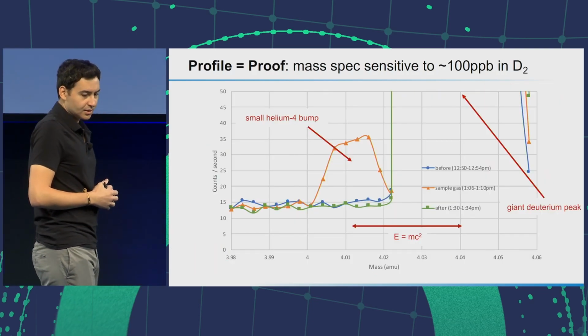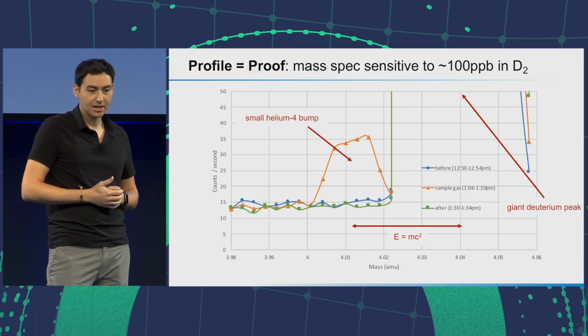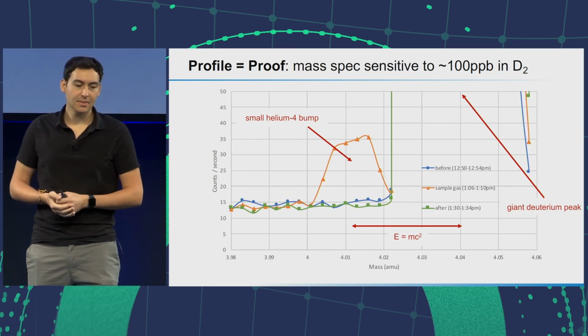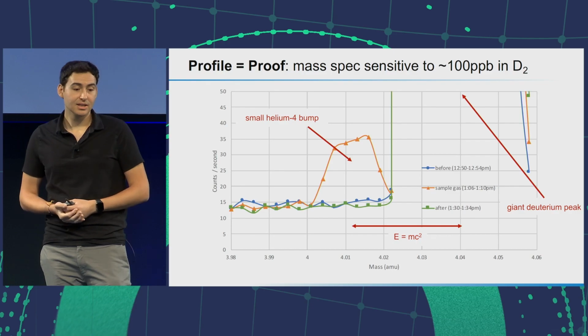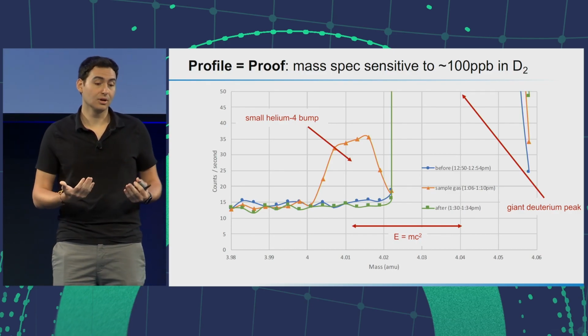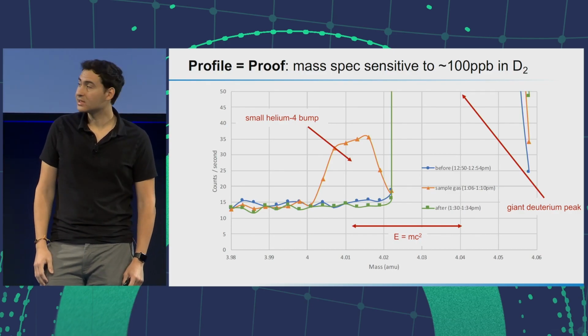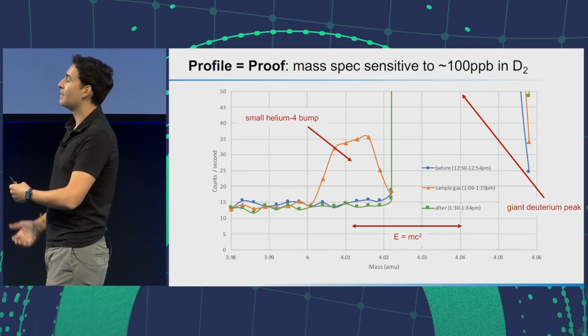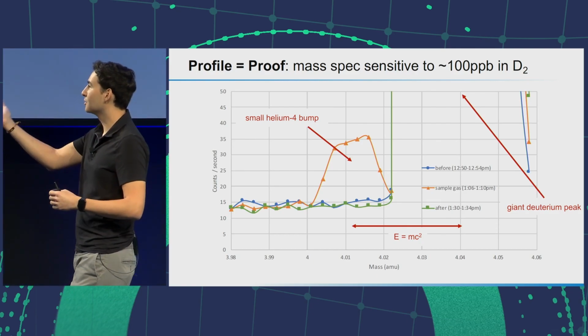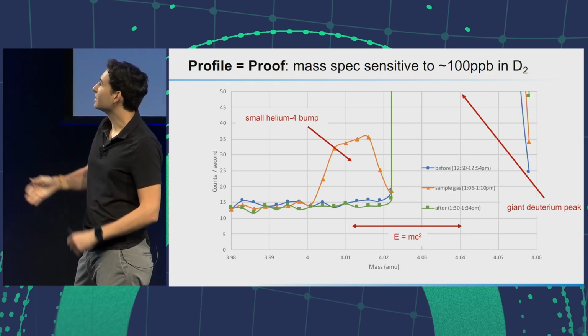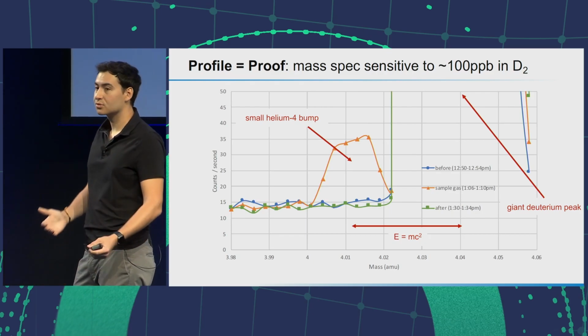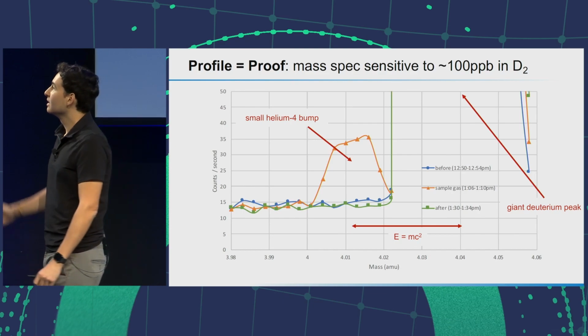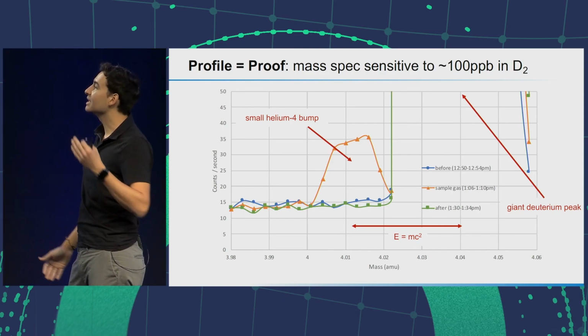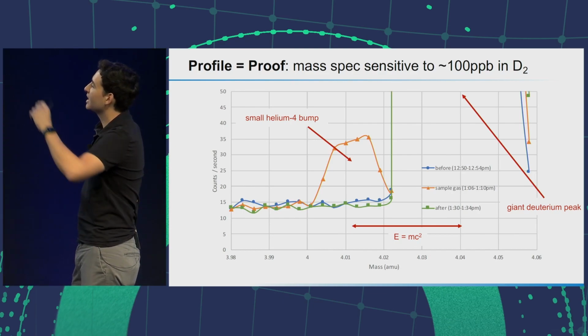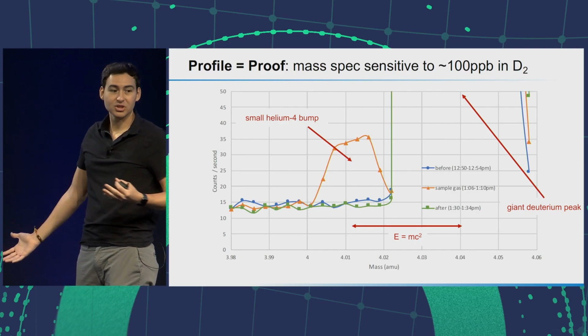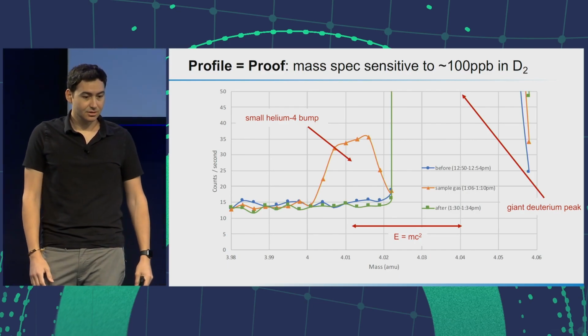So in terms of the actual detection for us, profile equals proof, meaning the mass spec profile is what constitutes the smoking gun for our approach. And so what we're seeing here is counts per second as a function of mass. And we could see very nicely E equals mc squared. That's wonderful. This giant peak on the right is deuterium because we are flowing in a deuterium environment. This goes way off the chart up to 10 million counts per second. And this little bump right next to it in orange is helium, which is what we're after. And you could see it in orange.